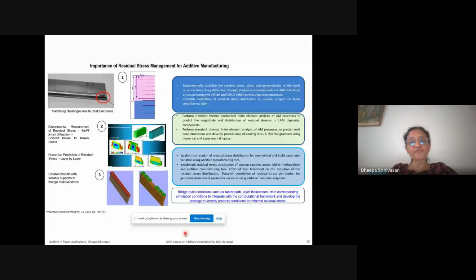Now, when we move on further to scale up, and say we are successful with the microstructure, successful without any texture, successful in the mechanical properties and the surface roughness, then the next thing would be to go from an experimental coupon level to a larger scale, obviously, in the build plate. And this is where there is another big challenge to watch out for in the qualification. As you increase the number of parts in the build plate, you can have distortion because the heat transfer is different when you're making one or two parts compared to making 20 or 30 in the build plate. Because of residual stresses and the heat transfer, in scaling up the number of parts, we also faced that.